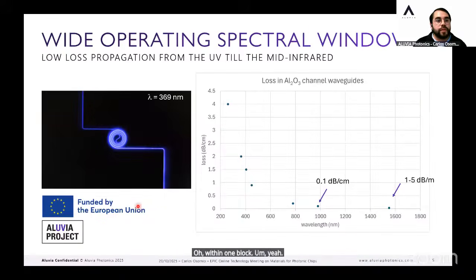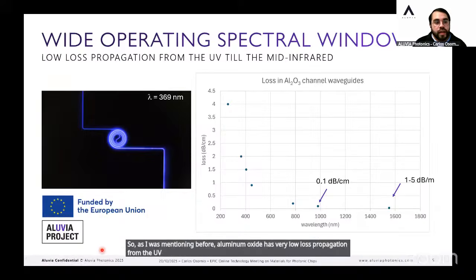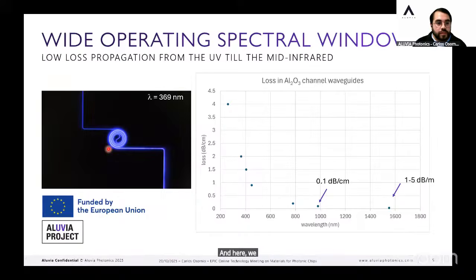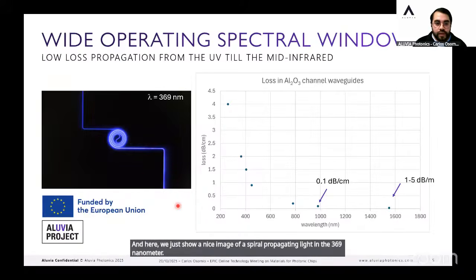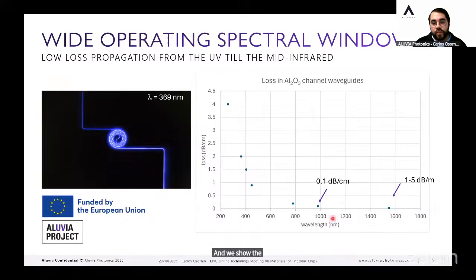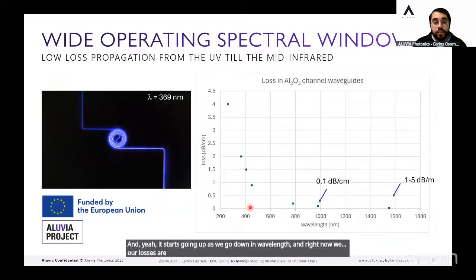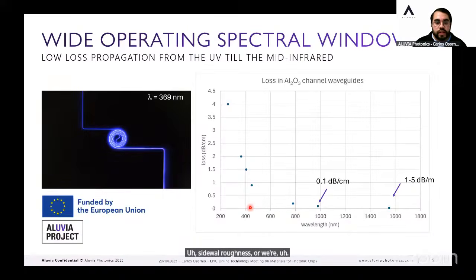As I was mentioning before, aluminum oxide has very low loss propagation from the UV to the mid infrared. Here we just show a nice image of a spiral propagating light at 369 nanometers. And we show the loss as a function of wavelength. We see here the very low loss at 1550, and it starts going up as we go down in wavelength. Right now our losses are dominated by the sidewall roughness, so we're working to reduce this roughness and further decrease these losses.